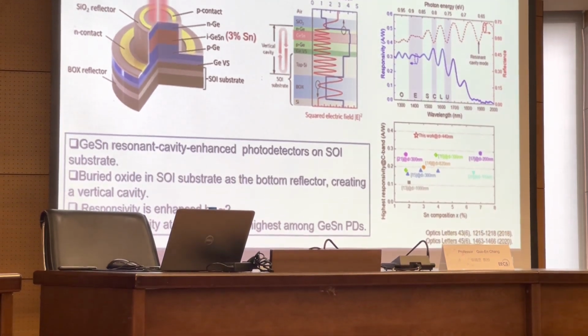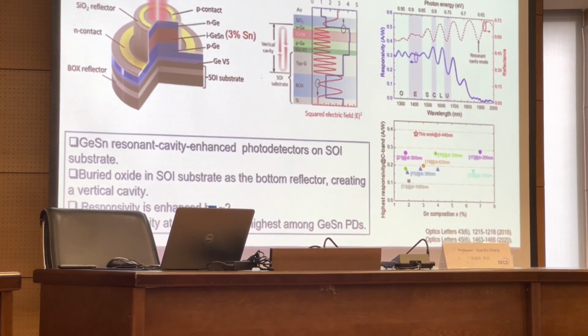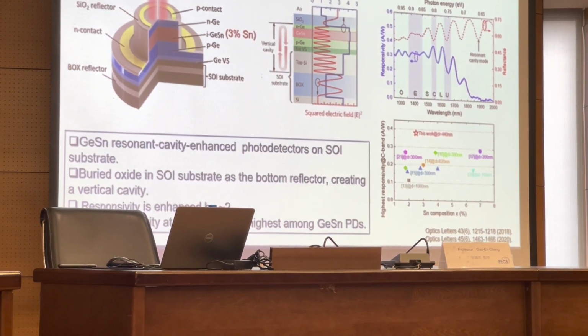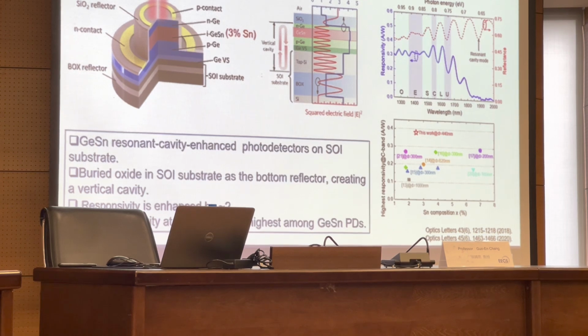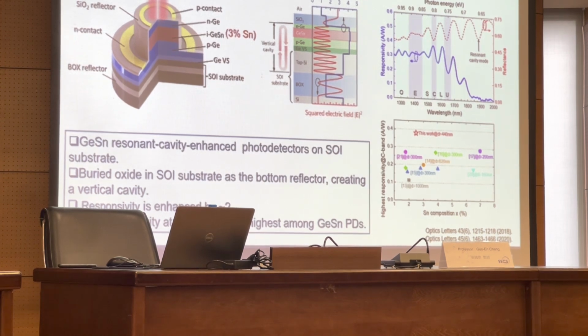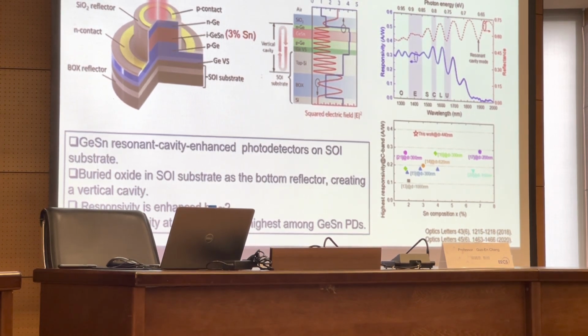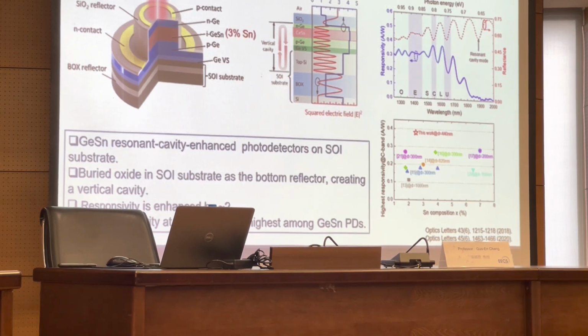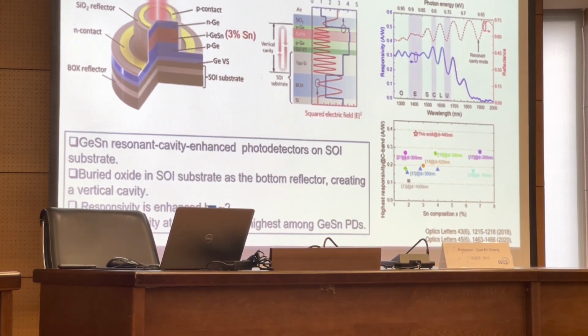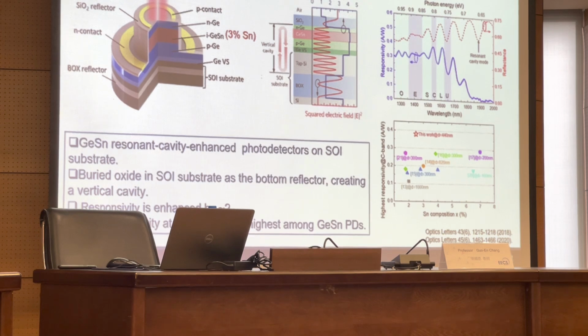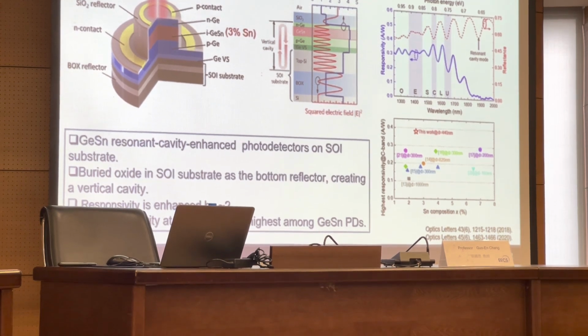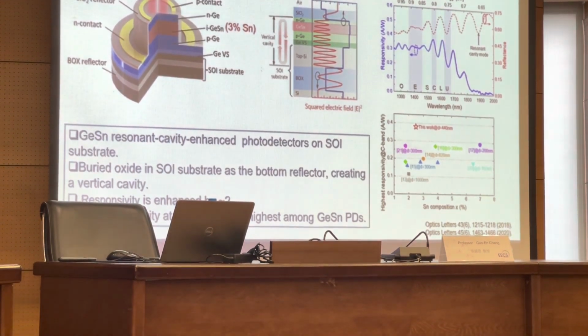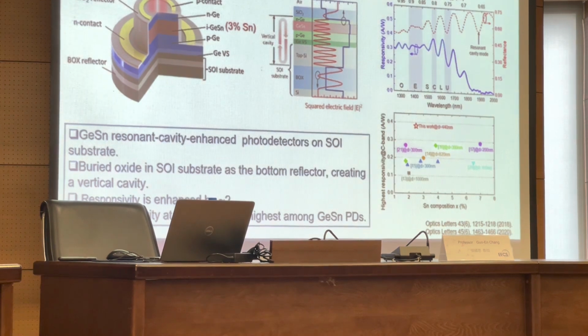From the measurement, we can see a resonance peak, which is due to the resonance cavity effect. Using this effect, we can enhance the responsivity by a factor of 2. This is our new work on the first GeSn resonant cavity enhanced photodetector.